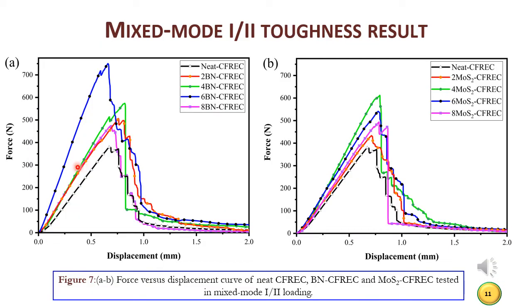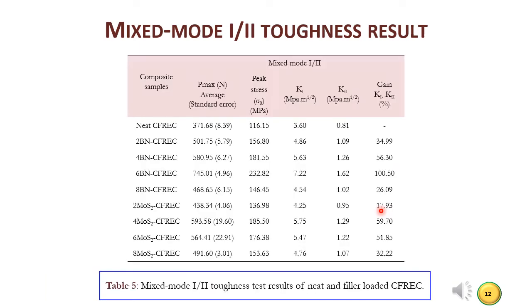Force versus displacement behavior of mixed mode test is represented in figure 7a and 7b. It is evident from the graph that stiffness and peak load of BN loaded CFREC are higher compared to MoS2 loaded CFREC due to the higher stiffness of hBN. The abrupt load drop in 8% filler loaded CFREC indicates brittleness of composite. The maximum stress intensity factors K1 and K2 of 7.22 and 1.62 MPa square root meter are obtained for 6BN CFREC.